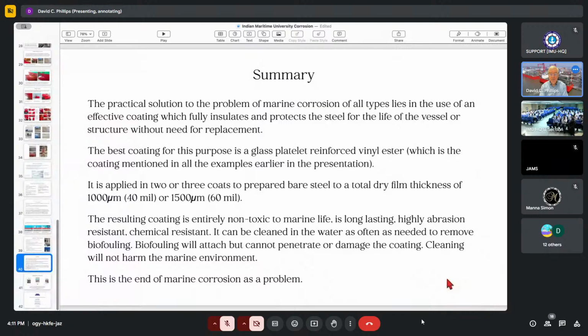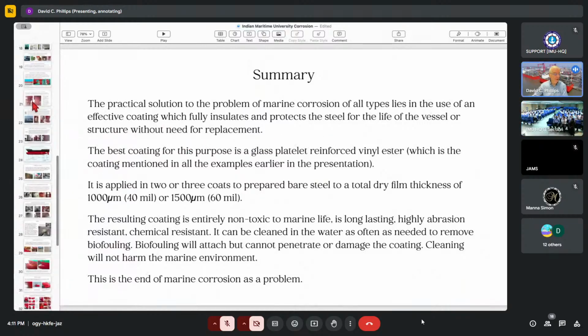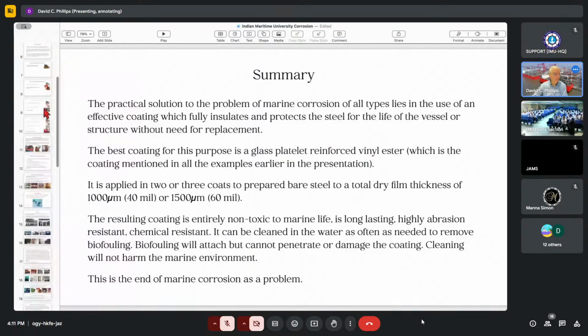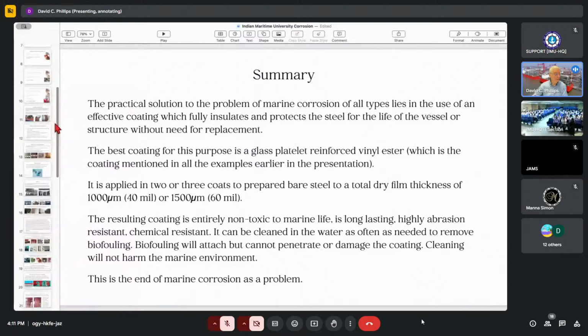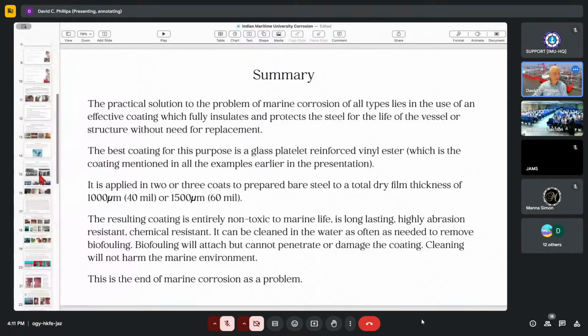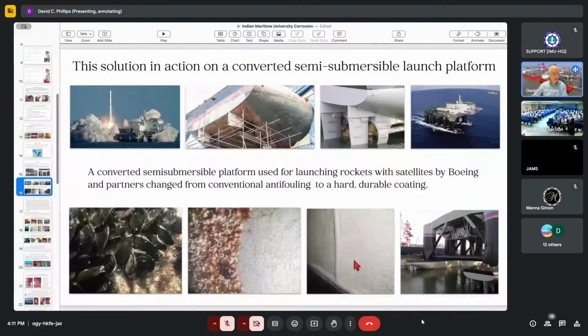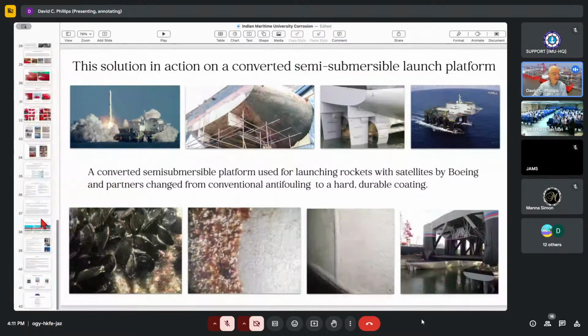It needs to be abrasion resistant because there's always going to be some kind of abrasion. Chemical resistant, particularly where there's a chemical situation involved. This coating can be cleaned in the water aggressively with heavy fouling as often as needed to remove the biofouling. And I showed you some of that earlier. Here, you see this coating. It's 10 years after it was applied, and it's been cleaned many times because it fouled many times. So that's a key factor.